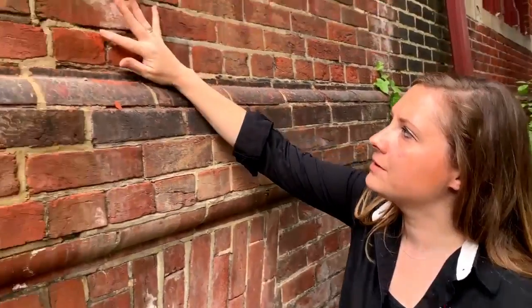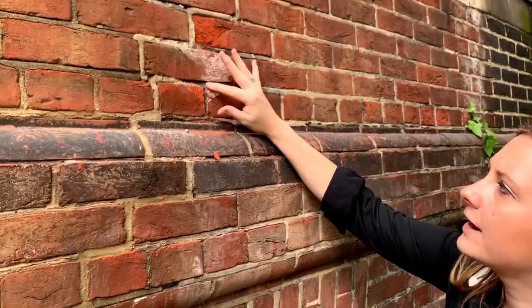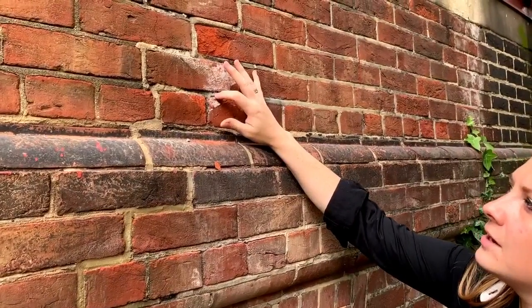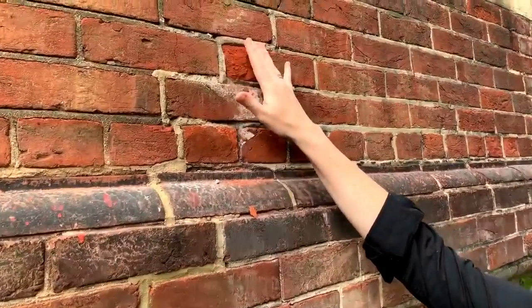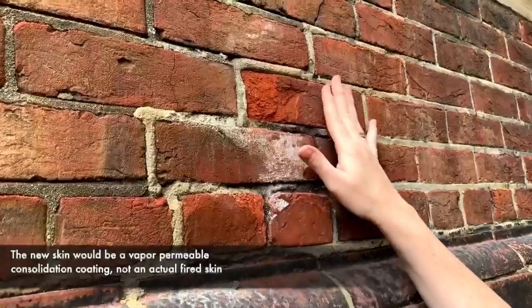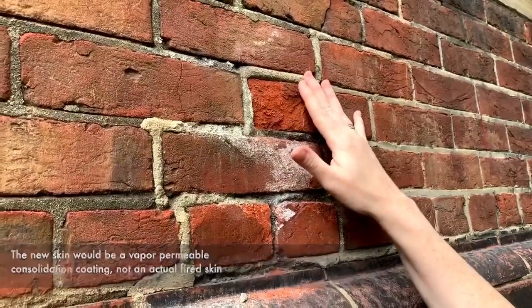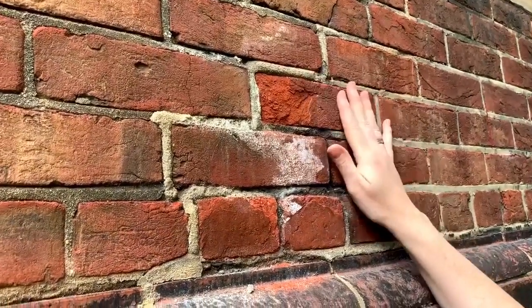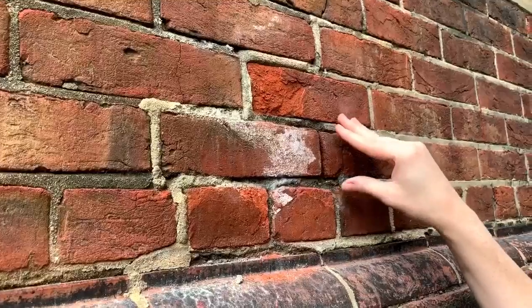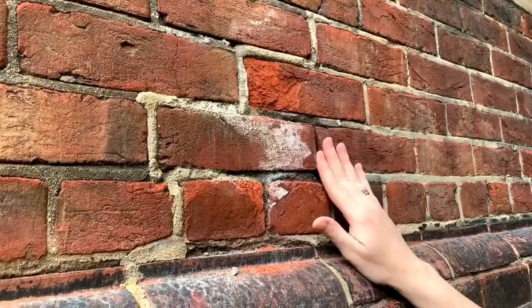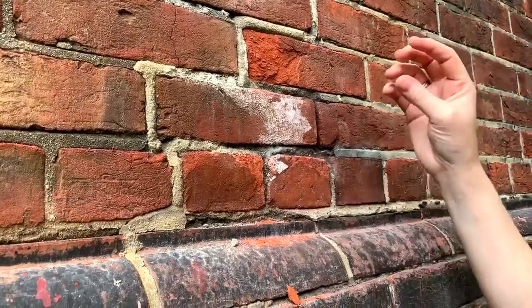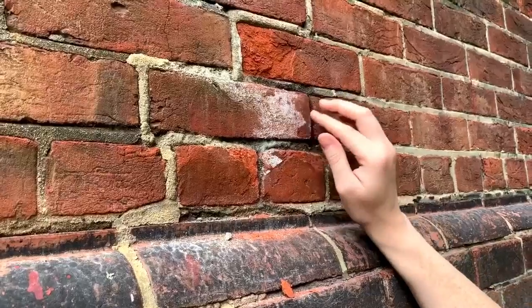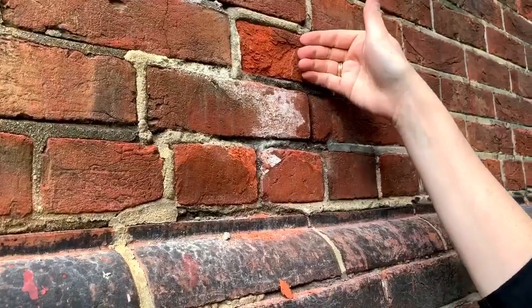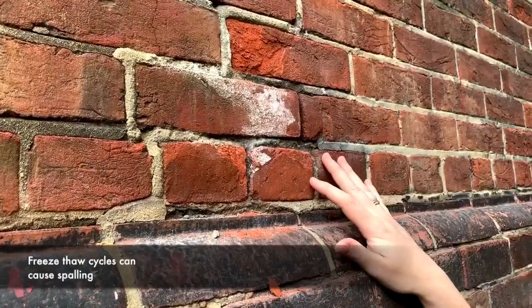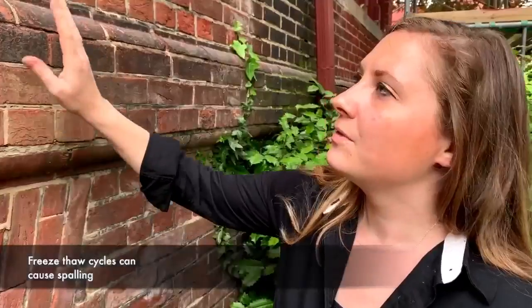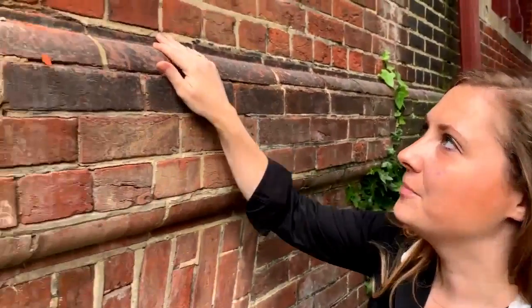We can repair this with brick patch or a new fired skin. However, the hard Portland cement mortar does need to be removed before any of this is done because this will continue to happen, especially when you have specifically wet winters. A wet winter would be bad because as water goes into the brick and then freezes overnight, in some cases it can actually pop the whole face of the brick off. This can be repaired, not all hope is lost.